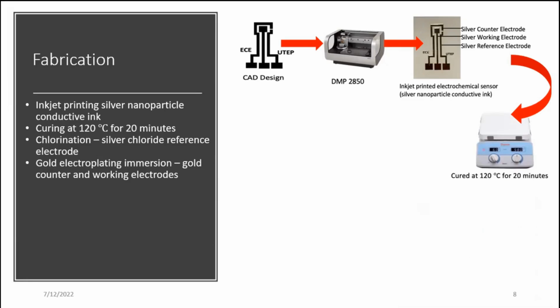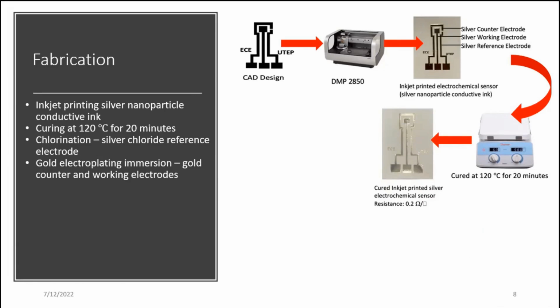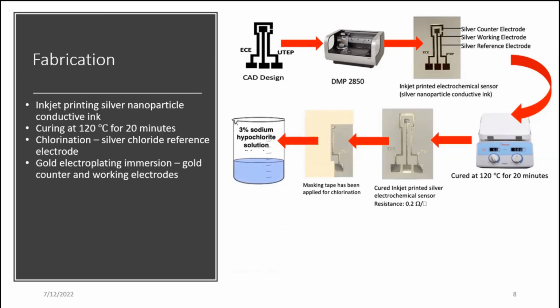So we pretty much put the printed pattern on the hot plate, where we cure it at 120 degrees C for 20 minutes. After that, our electrodes are conductive, and we get the resistance as 0.2 ohm per square, and this is for 2 layers of printing. And we cover the working and counter electrode with a masking tape, and only the reference electrode is exposed, and we expose it deliberately to do the chlorination process, because we want the reference electrode as a silver chloride reference electrode. But here also we need to be very careful. We can only immerse the reference electrode for 30 seconds, because if we exceed the time, it will break the electrode and we might compromise the conductivity.